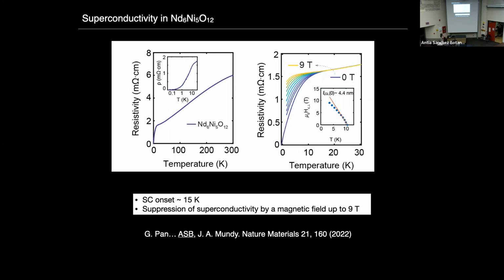So this here is a snapshot of the experiments done by Julia's group on films of neodymium 6,5,12, which is again the 5-layer nickelate. You see at first the resistivity versus temperature, where we have once again a superconducting transition whose onset is once again at around 15 Kelvin. Not much better, but there may be room for improvement with improvements in the materials, which are ongoing.